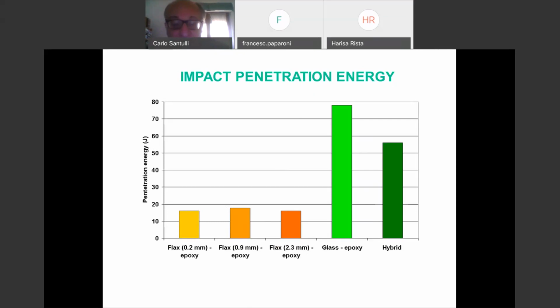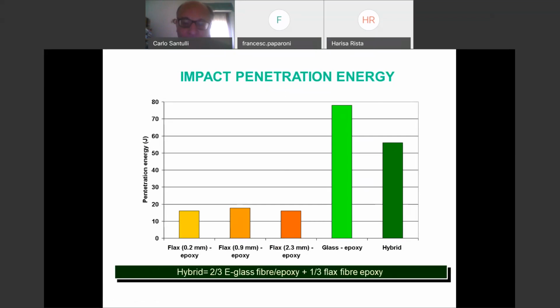What is really obvious is that the 0.9 flax epoxy, 0.9 diameter of the thread, the flax thread, gives you a larger penetration energy. Then, with respect to glass epoxy, the hybrids are very far. So you can imagine that impact is still a problem. But if we make a hybrid, in this case, the hybrid was made with 0.9 flax epoxy and glass fibers of two-thirds to one-third. The properties are much closer to glass than to the flax epoxy.